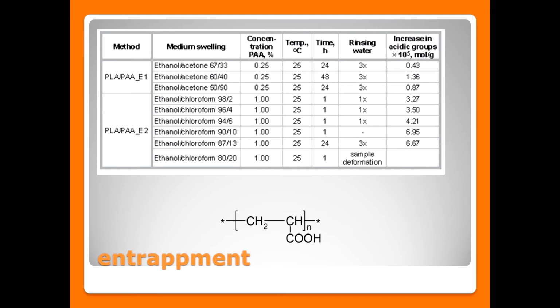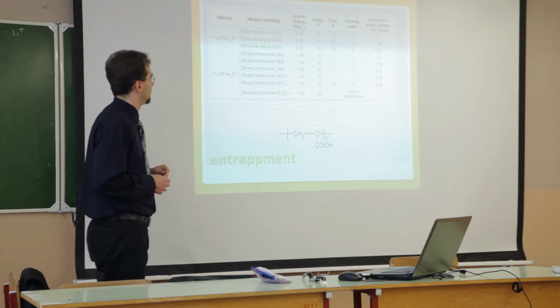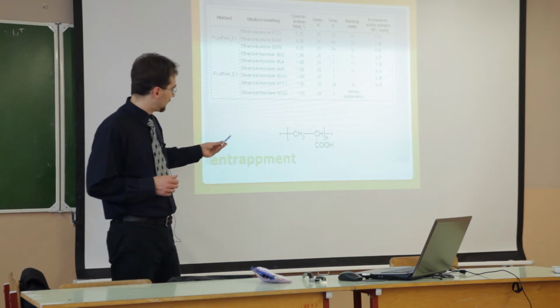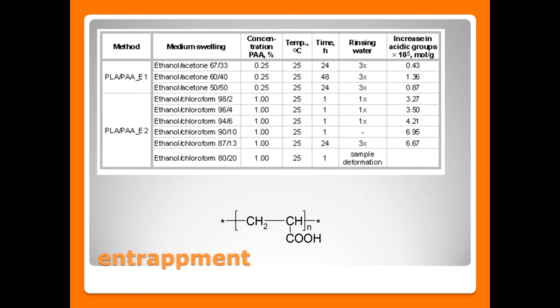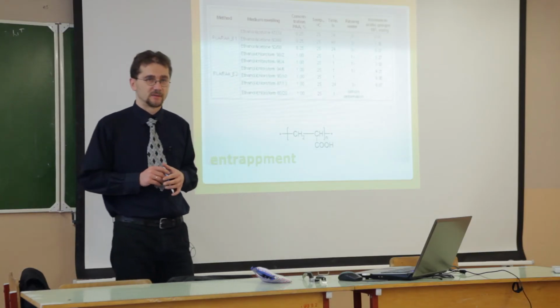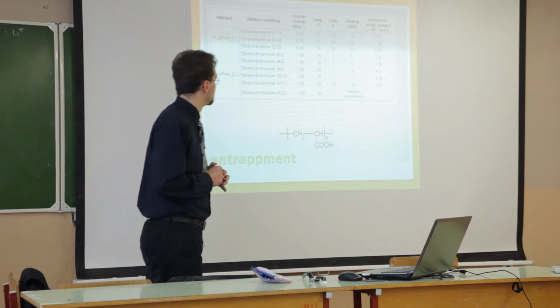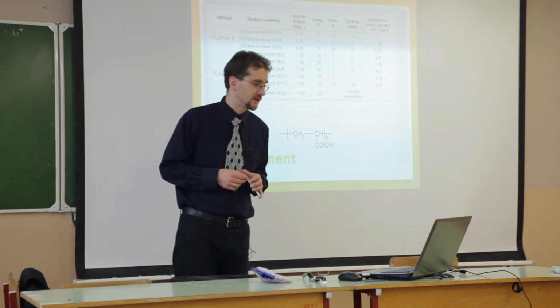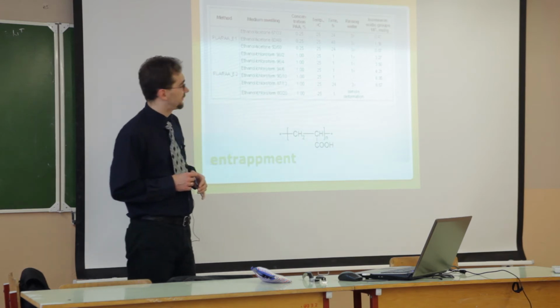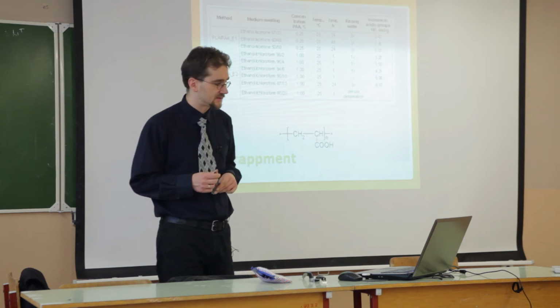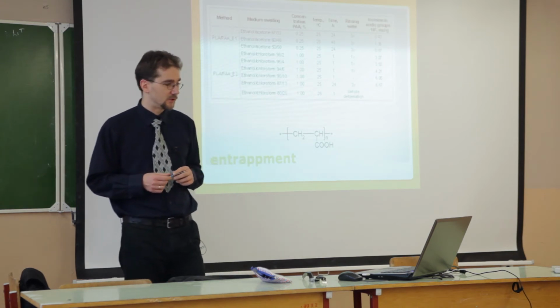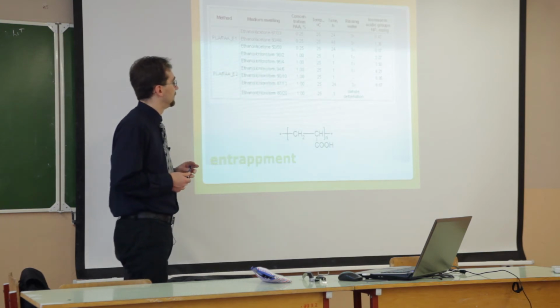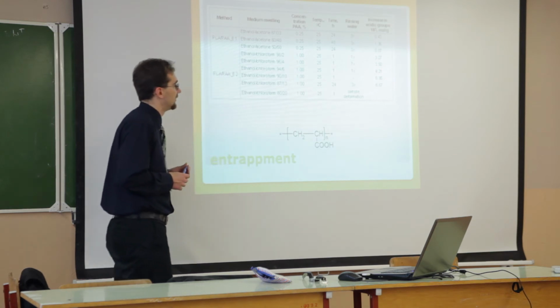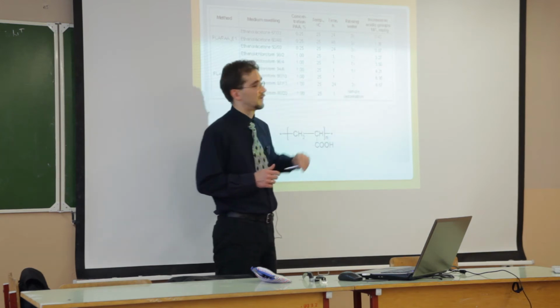As a mixture of non-solvent and solvent, we use ethanol-acetone and ethanol-chloroform, and again polyacrylic acid is our main polymer, which we would like to introduce onto the surface. We used different concentrations of polyacrylic acid, from 0.25% to 1%, and different times, even very long ones, for example 48 hours. We rinsed the material with water a couple of times, and found that in each process we could achieve some number of acidic groups on the surface.